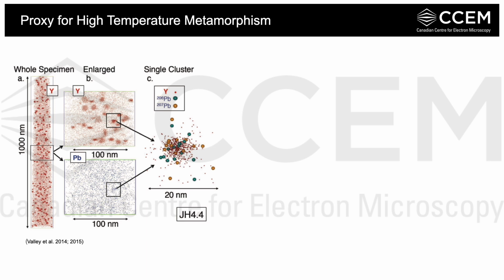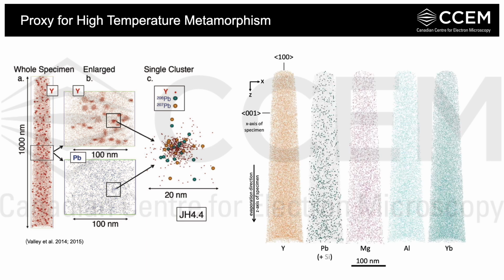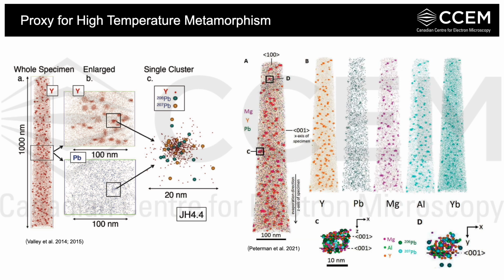It has been also demonstrated experimentally using crystalline unheated zircon that these trace elements remain homogeneously distributed, while when we heat the zircon in the laboratory at around 1400 degrees Celsius for 24 hours, we now see dislocation loops in our grain that are decorated with these trace elements, including lead.